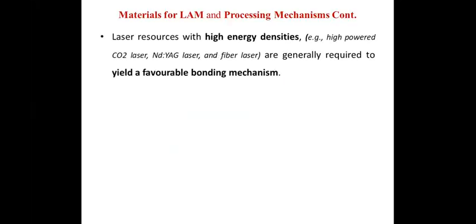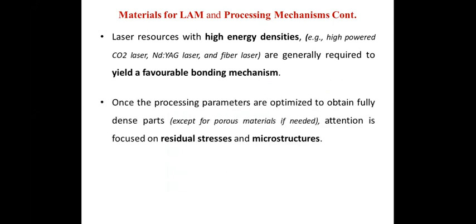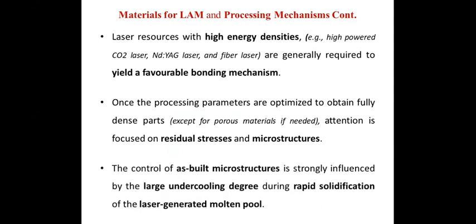Laser sources with high energy densities are generally required to yield a favorable bonding mechanism. Once the processing parameters are optimized to obtain fully dense parts, attention is focused on residual stress and microstructures. The control of the as-built microstructure is strongly influenced by the large undercooling degree during rapid solidification of the laser-generated molten pool.